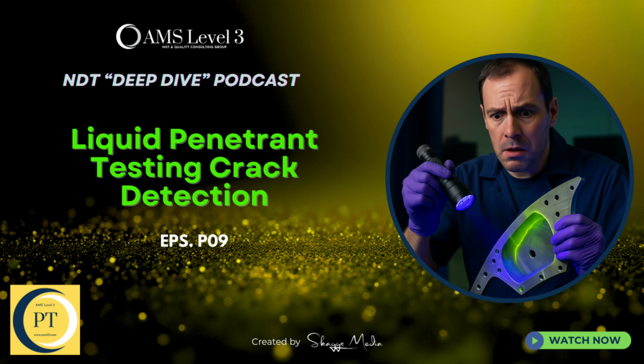intense. Okay. Now, very tight cracks, like maybe new fatigue cracks, sometimes they don't form a solid line right away. They might appear as a series of very small, distinct dots, but lined up in a continuous formation, still linear, just dotted. Interesting. What about flaws that aren't cracks, like holes or something? Right, like porosity. Those are usually small gas pockets trapped in the metal. They typically show up as multiple rounded spots, maybe scattered across an area, pretty distinct from a line.